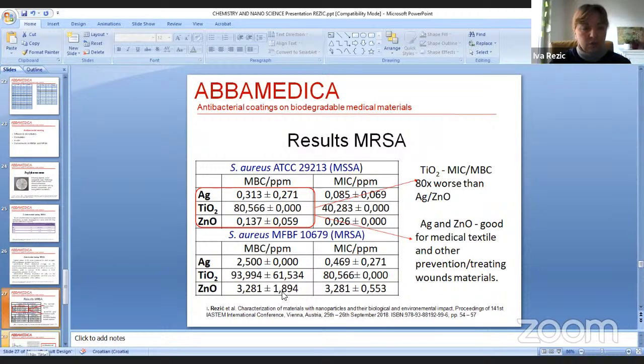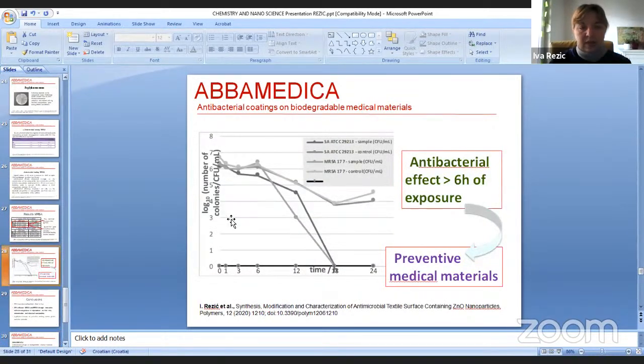What did we do? We took tests at different hours, and as you can see in this graph, after 6 hours, a really strong effect starts. So after 6 hours of exposure, all these unwanted microorganisms will be killed on the surface of materials, which actually proves that our materials with such coatings are excellent preventive medical materials which can be thoroughly investigated for this purpose.